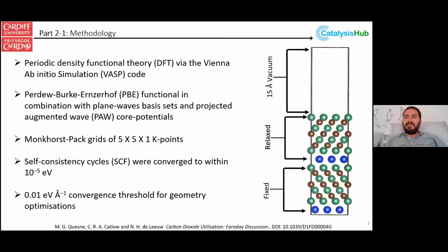For this study, we decided that we needed quite a big slab to get away from any perpendicular dipole. So we decided to have a slab where we have 6 layers that are frozen and 6 layers that are allowed to react. The 6 bottom layers are there to represent the bulk. And then we have 6 layers that are able to adapt to adsorbates and the reaction mechanism, and these kind of simulate the surface. We use the PBE functional. We did some benchmarking previously with the related monocarbides, and we found that PBE really was as good as most of the other GGAs at representing the properties of these materials. And there's always a trade-off in DFT between the theory that you use and what you can do.